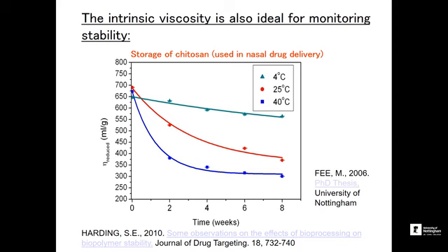So intrinsic viscosity or reduced viscosity measurements are a very simple way of checking for stability of macromolecule based drugs. Not so much for spherical molecules, unless you're looking for denaturation. It's not very good for looking at degradation, because the intrinsic viscosity for globular proteins doesn't change much with change in molecular weight degradation.